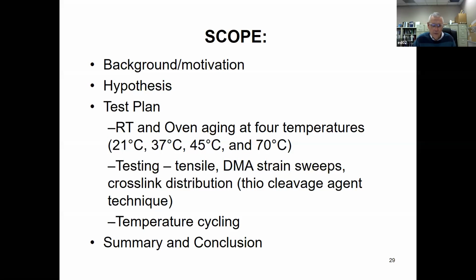And so we have this outline, or this test plan. Okay. So first, just talk about the motivation and background for this project, and then our hypothesis. And then the test plan is room temperature and oven aging at 4 temperatures: room temperature, 37 degrees, 45 degrees, and 70 degrees. And the testing includes tensile, DMA, strain sweeps, and our crosslink distribution wet chemistry thiol cleavage agent technique. And then we also did what we called temperature cycling.